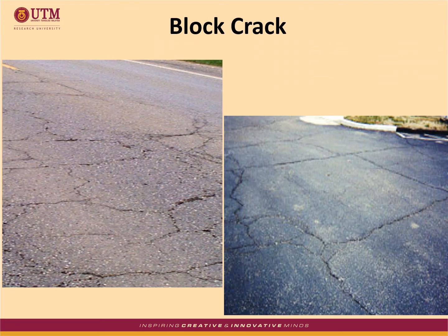Okay, this is block cracks. It looks like large interconnected rectangles, which is caused by the shrinkage of the asphalt pavement due to the inability of the bitumen to expand and contract with temperature cycles. This can be due to the use of low penetration bitumen and poor choice of bitumen in the mix design. For treatment, similar to the previous type of cracks, less severe cracks can be sealed to prevent water penetration, and more severe cracks can be fixed with an overlay.